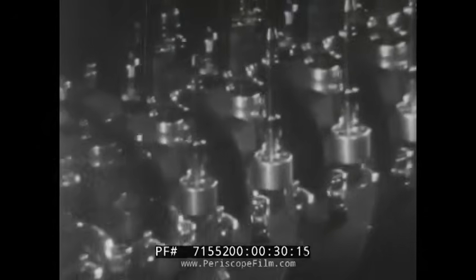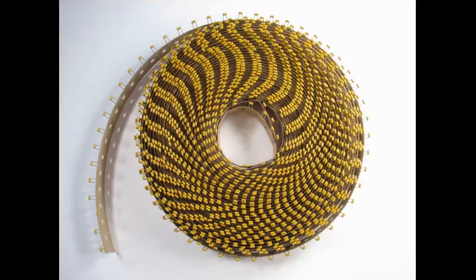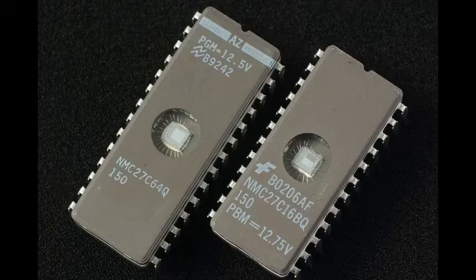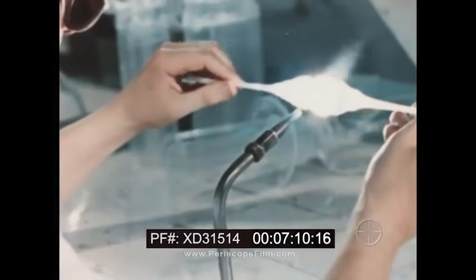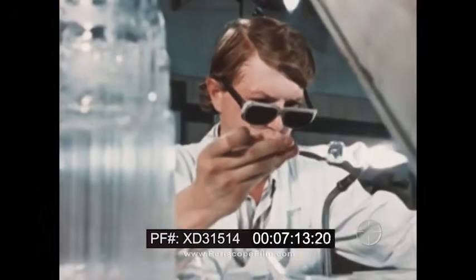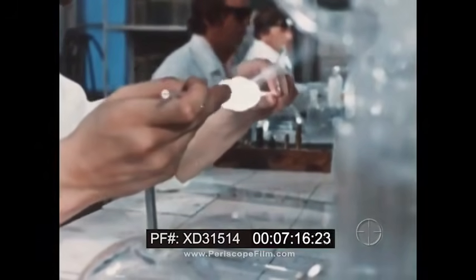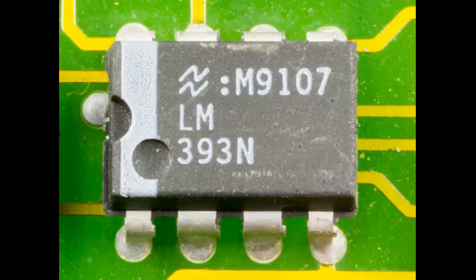The first expansion was electronics. Alumina has been used in electronic packaging since the 1940s because it can support conductors while insulating them from one another, withstand heat from components, remain dimensionally stable, and form hermetic bonds with metal. Instead of carrying one electrode through a spark plug, ceramic packages could carry many electrical connections into sealed devices. Manufacturers learned to metallize alumina by applying specially formulated metal pastes and firing them so they bonded to the ceramic. Metal frames, pins, and lids could then be brazed into place. The resulting package protected sensitive electronics from moisture, contamination, vacuum loss, and mechanical damage.